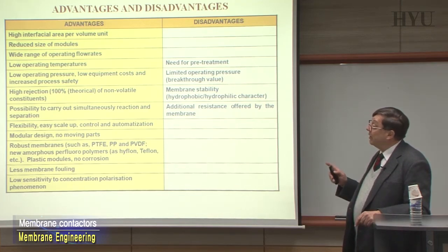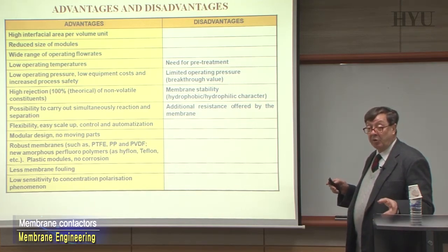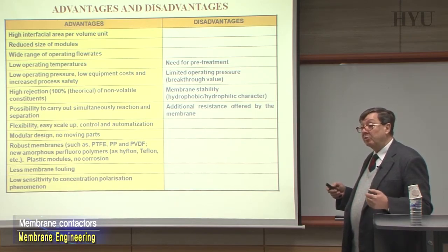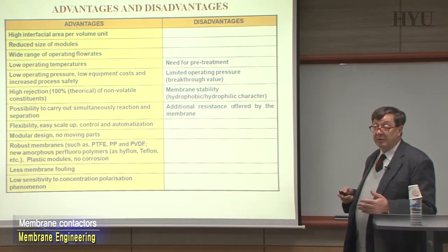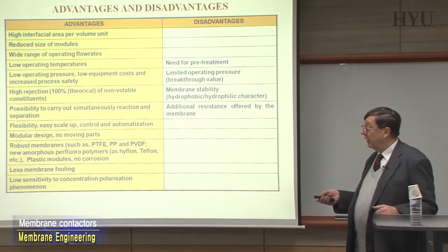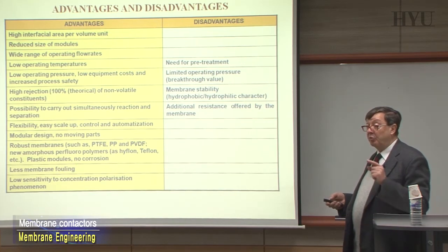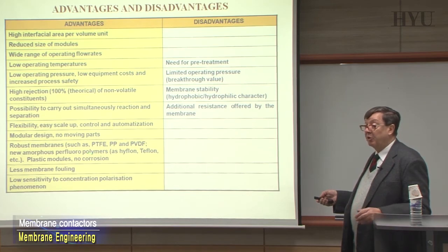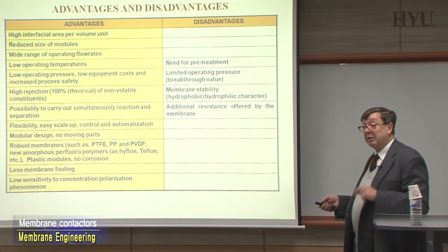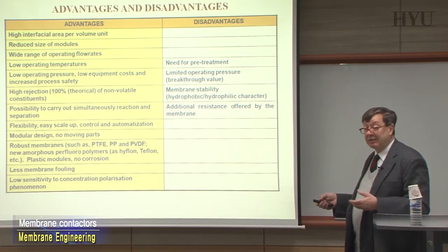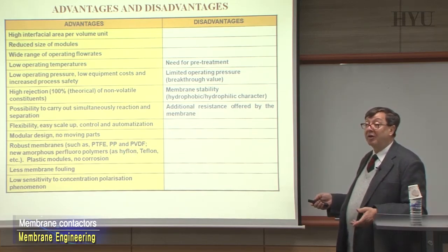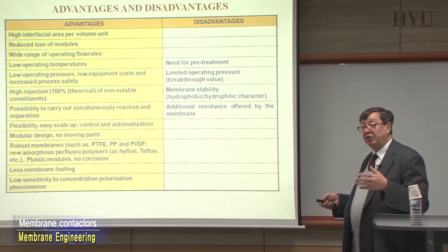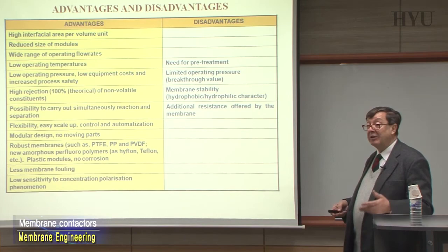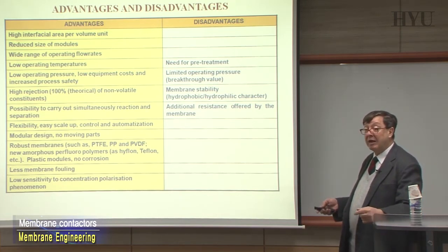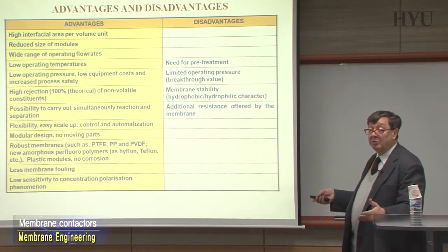For example, the membrane has to be hydrophobic, microporous but hydrophobic. If anything can induce a decrease of hydrophobic character, transforming it from hydrophobic to hydrophilic, this is the kind of fouling that we have to take care of. That's why we are using, as much as possible, strong amorphous perfluoropolymers, which have a very significant hydrophobic character, but are also resistant to chemical attack. Polypropylene is not the best one, for example, because polypropylene can easily interact with alcohol, surfactants, with different kinds of chemicals, and lose hydrophobic character, becoming hydrophilic. That means this is big fouling, you cannot operate anymore.